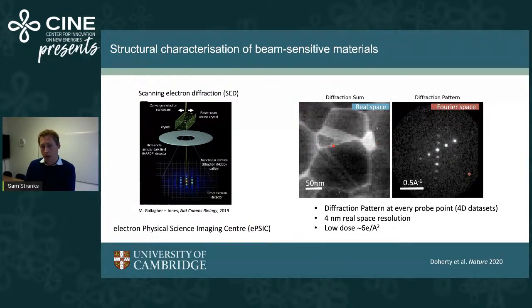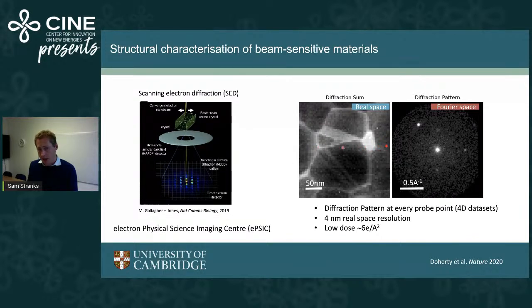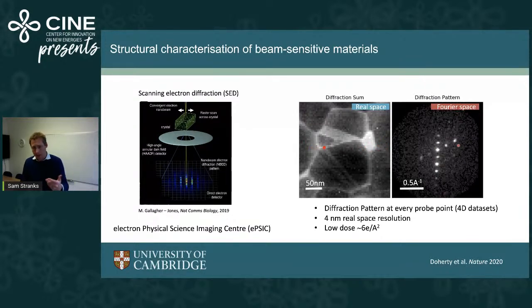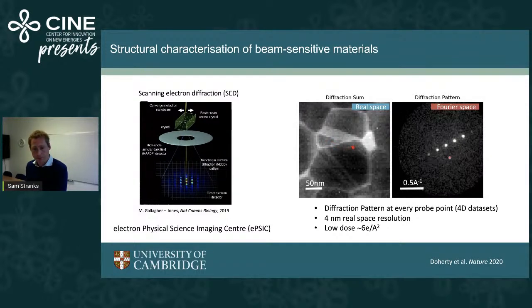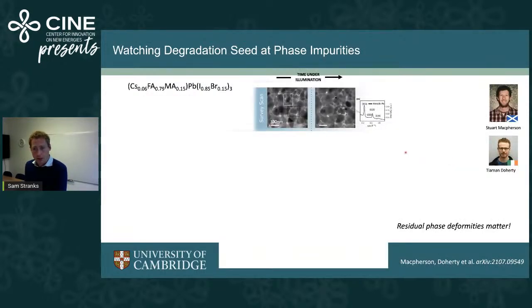What's quite surprising and quite important is that even just as you scan across this grain, just how much variation there is in the structural properties. And so here I'm going to show some measurements where we're illuminating over time and degrading these samples and really trying to understand what the structure is. So building on the data I showed a few slides ago, this is before and after illumination. And what you see is that most of the film is unchanged, but there are certain regions, such as here, where there are changes and there are things happening, and I'm going to delve into that a bit more.